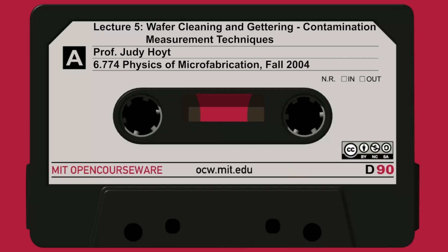But the bird's beak shape is actually due to lateral oxidation, some of the oxidant diffusing in here under the nitride mask. And its shape is also controlled by the nitride mask pushing down on it. So the oxide's trying to grow, it has to push up on the nitride, and that takes some force. So this whole shape and the amount of lateral encroachment is very much dependent on the stress effects, and we'll talk about that in the next couple of lectures. So complex shapes can be formed by local oxidation.